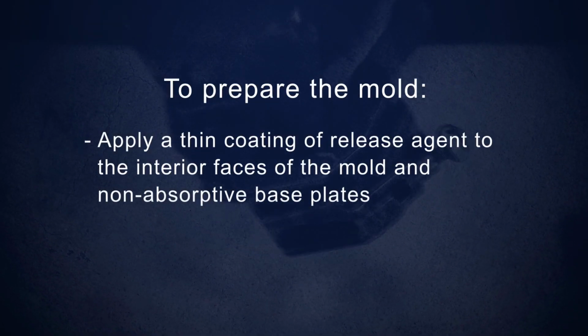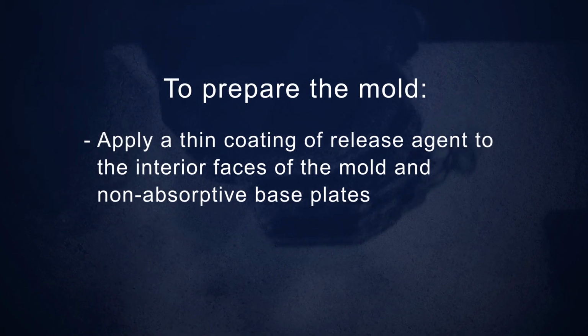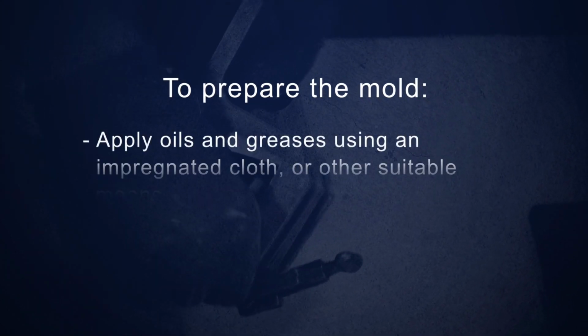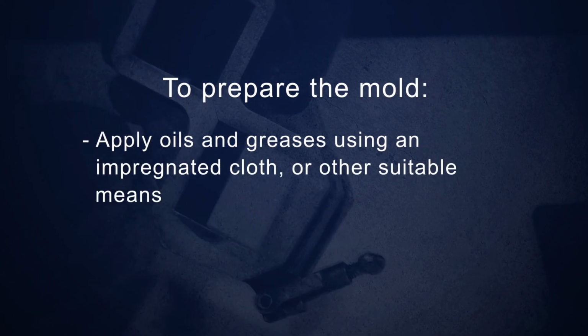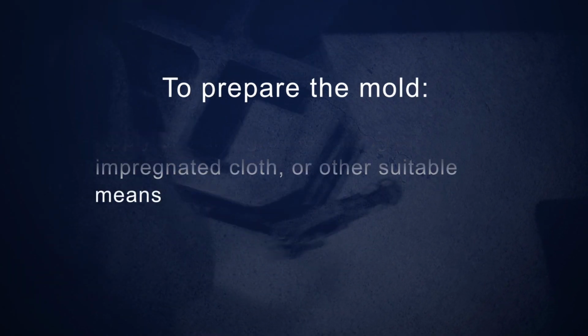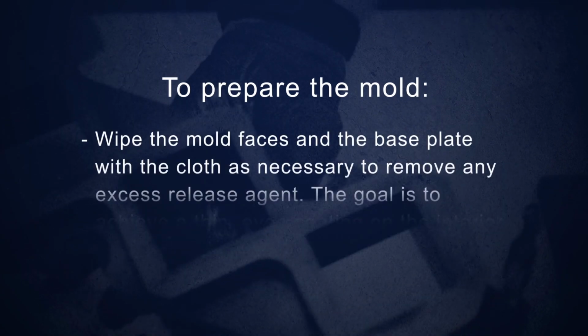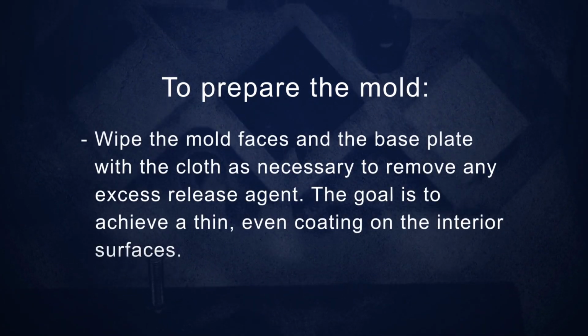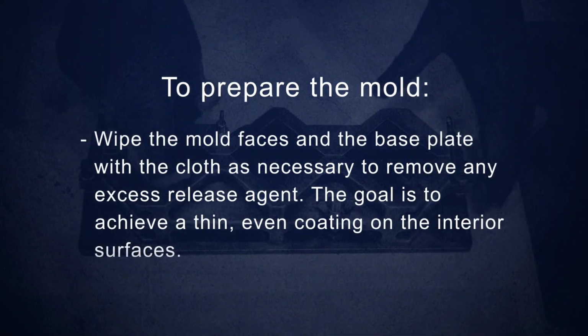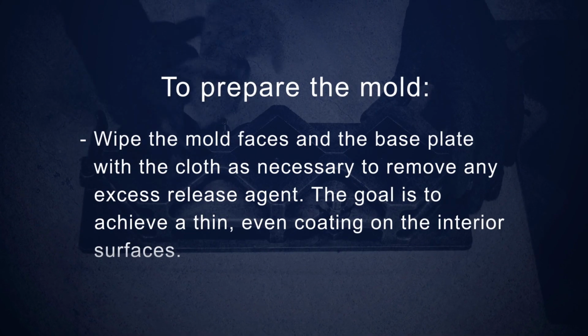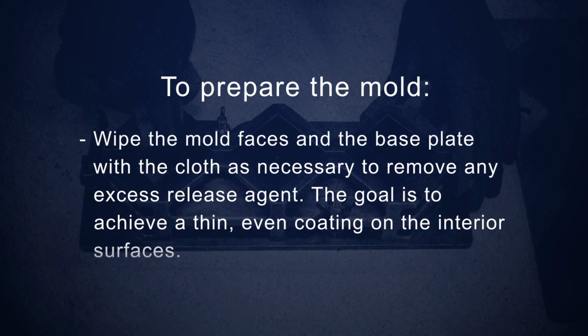To prepare the mold, apply a thin coating of release agent to the interior faces of the mold and non-absorptive base plates. Apply oils and greases using an impregnated cloth or other suitable means. Wipe the mold faces and the base plates with the cloth as necessary to remove any excess release agent. The goal is to achieve a thin, even coating on the interior surfaces.